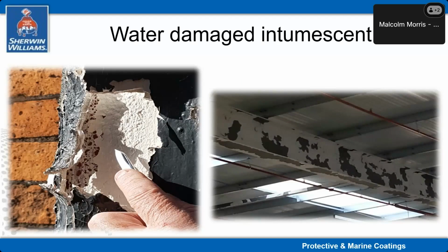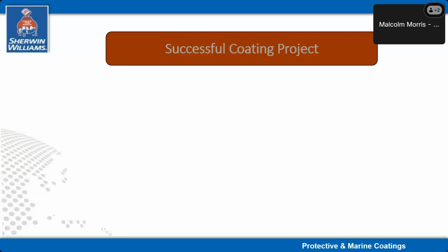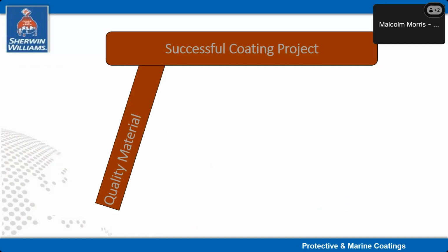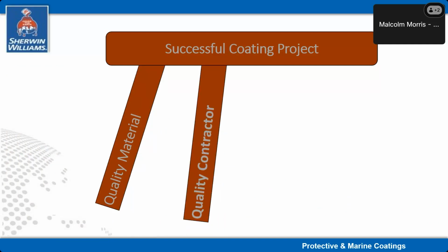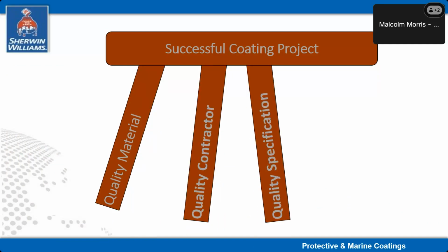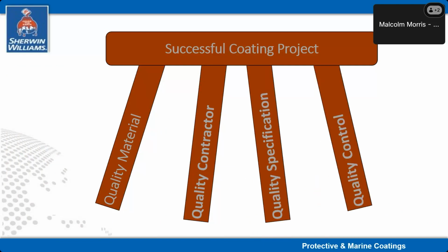But typically intumescent, you can see that the beam on the right hand picture where the coating was applied under poor weather conditions, and the coating broke down comprehensively as a result. So any successful coating project depends on quality at every stage. So quality materials, quality contractors, quality specification, and most importantly, quality control. And if you get those four aspects of quality lined up and coordinated by properly trained people, then you will have a successful coating project, which is what we're all after.